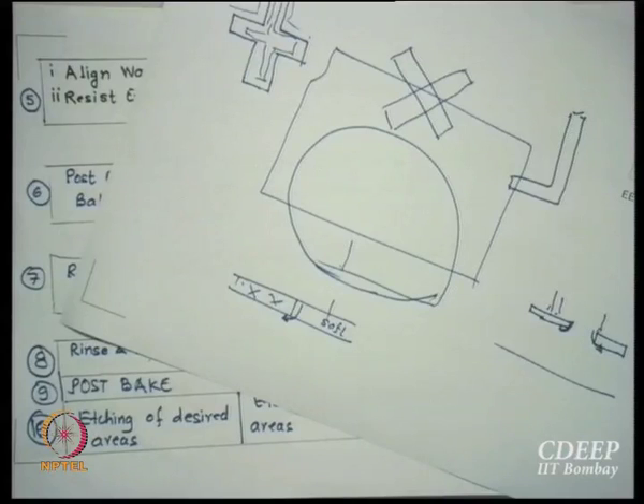So if it's too long, development can also pull the hardened resist areas, and therefore 30 seconds is, we figured out, enough that the hard portion remains there itself. Otherwise, from below, something like this, the developer goes through below and just takes it away, so the plain wafer will come, there is no resist anywhere, okay. So this trick of time and temperature is very crucial, and thickness, how much you have put, that decides the time and temperatures.